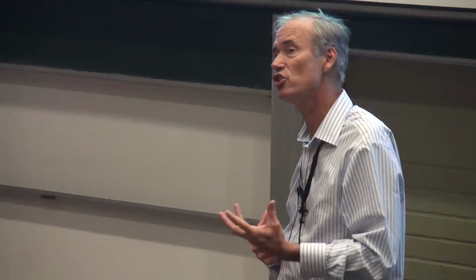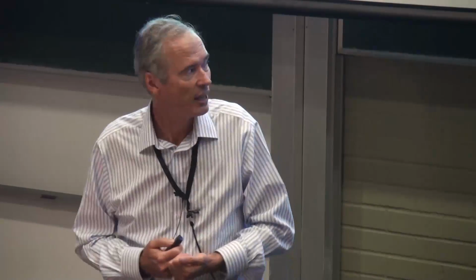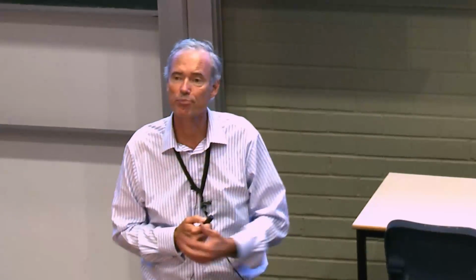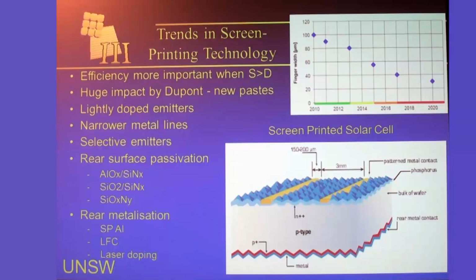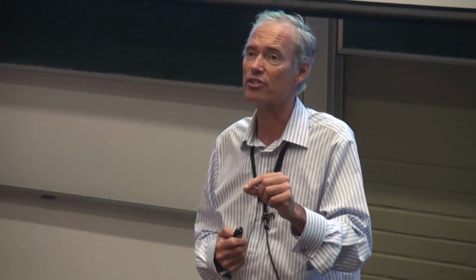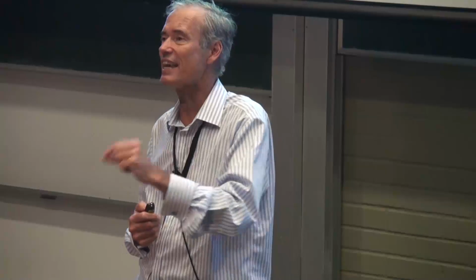In fact, we saw some very interesting results at the conference that I've just come to. That's the European PVSEC conference. And on P-type Czochralski, there are now reports of voltages getting close to 700 millivolts by using good hydrogenation in the silicon wafer as a result of avoiding the use of the screen-printed aluminium metal. So that could be something that catches on, or companies may prefer to stick with the very simple screen printing approach. It'll be very interesting to see which way that goes. But I think the fact that P-type Czochralski silicon is now being shown able to get to voltages like 700 millivolts is really astounding a lot of people, and it's really astounding a lot of experts.